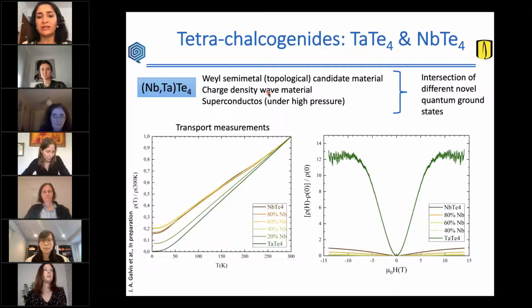And we found out that this charge density wave is not very well characterized in this compound, or at least there is no consensus on the charge density wave characteristics.